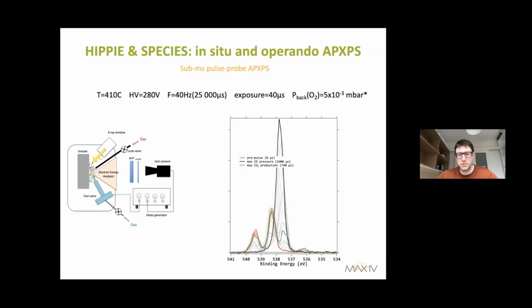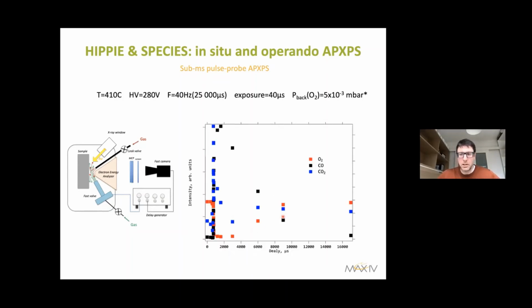The first interesting thing we could see from this experiment is that we do have oxygen before the pulse and then a lot of CO within the pulse, but we don't see, for example, oxygen within the pulse. It means that the gas that we are pulsing in this particular case, CO, completely blows away oxygen. That really helps us establish a difference in the chemical potential or partial pressure of several orders of magnitude and have this quick change from one gas to another gas.